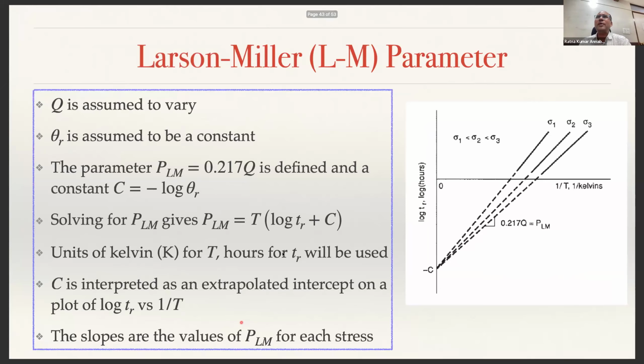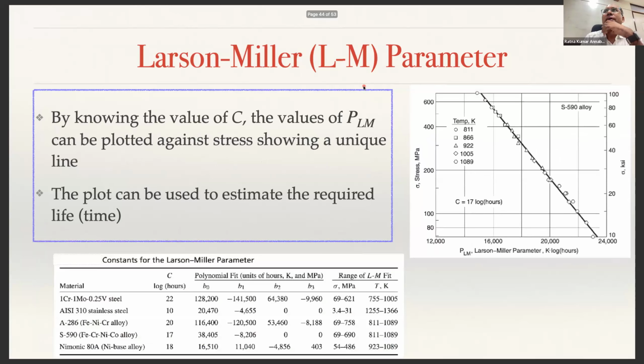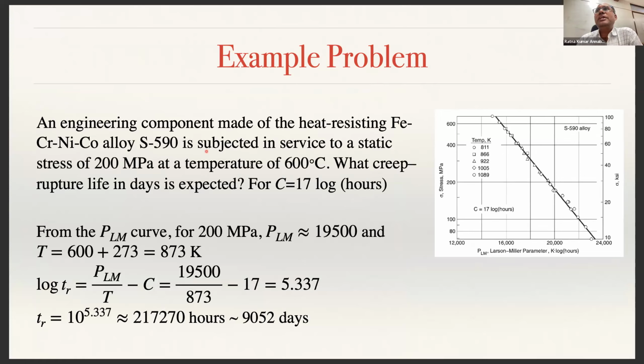Similarly, besides Sherby-Dorn, there is also another parameter called Larson-Miller, LM. This is also a very similar model, but a little different from the other one. I'm not going to discuss this, but if you go through the slides, it should make clear how it is calculated. Again, you can compute the life for the same material. If you are operating at 200 MPa at 600 degrees Celsius, again for the S590 alloy, you see that it is 9,052 days. So different models will give you different values, as we know already from other failure theories.